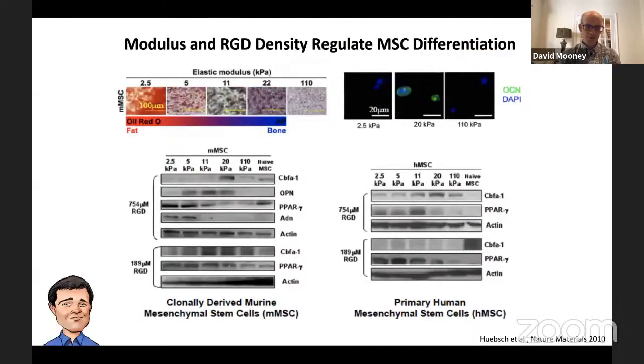Nate Huebsch, shown here in the lower left, who's now running his own lab at Washington University, was the first to demonstrate that in 3D, one could indeed regulate the fate of stem cells simply by varying the mechanical properties of the gel. So here he took MSCs. He put them in gels that were either very soft, as indicated by an elastic modulus of 2 to 2.5. And these cells actually differentiated and became fat-forming cells or adipocytes. In gels that were a little bit stiffer, the cells became osteoblasts or bone-forming cells. And in the really rigid gels, they actually didn't differentiate at all.